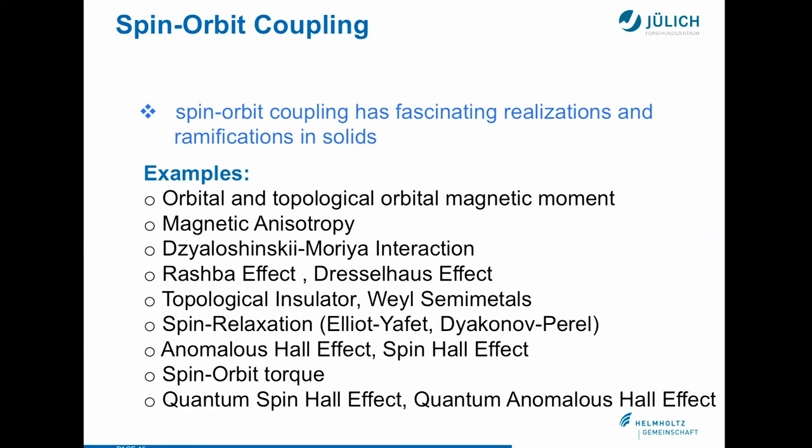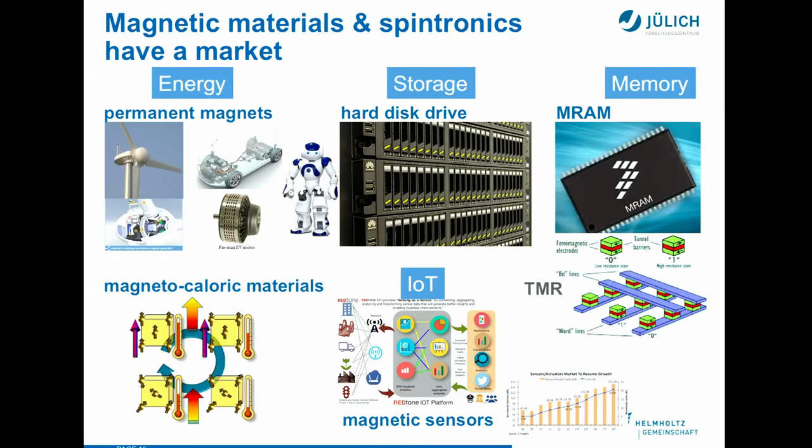And when I say it's a very small quantity, you mean immediately you need a lot of K points, you need precise calculations. And due to the spin-orbit interaction, of course, you also lift degeneracies. That means you need a bigger Hamiltonian. The Hamiltonian is not real anymore. It's complex, and so on. So the calculations quickly become time-consuming. And this aspect which I mentioned is part of a bigger field of magnetic materials and spintronics.